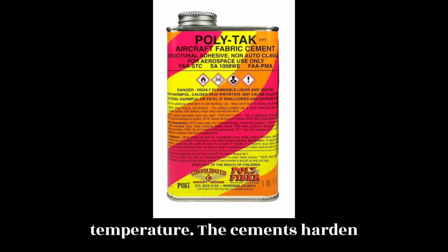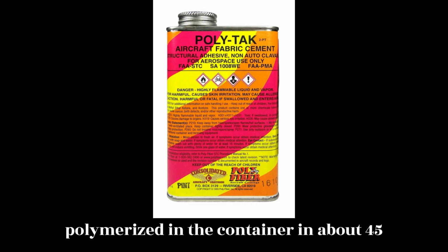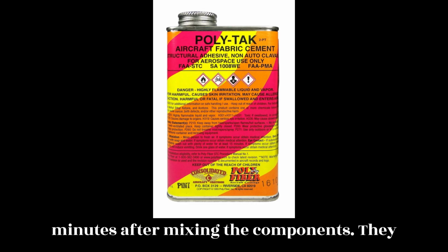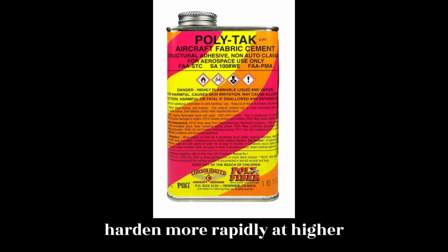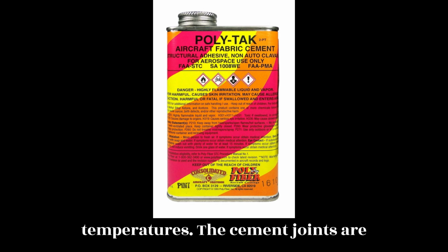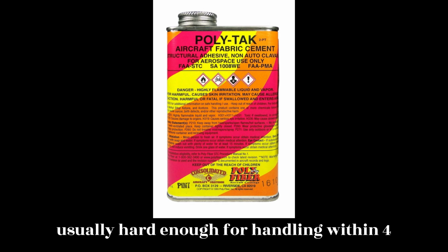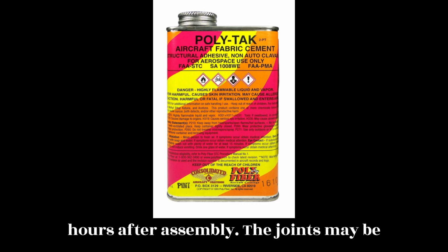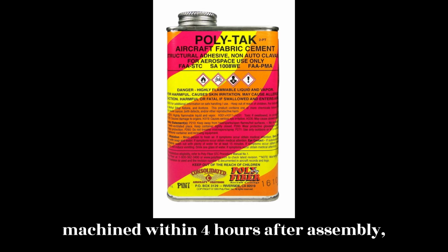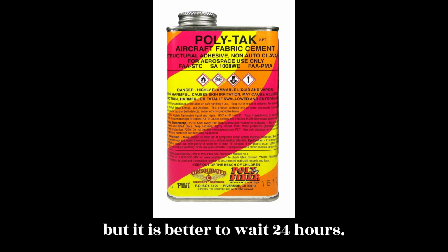At room temperature, the cements harden, polymerize, in the container in about 45 minutes after mixing the components. They harden more rapidly at higher temperatures. The cement joints are usually hard enough for handling within 4 hours after assembly. The joints may be machined within 4 hours after assembly, but it is better to wait 24 hours.